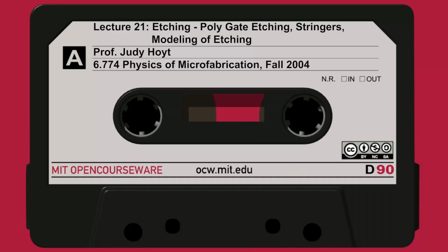On slide 2, this is a chart, or it's half of the chart that I took directly from chapter 10 in your text. And what it shows is a series of common materials and some typical etchants that are used, and then some comments about each of these etchants. For example, a very common way of etching polysilicon in a generic way is to use SF6 or CF4. What are the characteristics of that type of etch? Well, it tends to be isotropic or near isotropic, and not very good selectivity over SiO2. So once you hit the SiO2, you continue etching. So this is a general purpose etch you might use if you're trying to strip off some poly off the back of the wafer or something. Probably not something you might use if you need anisotropy or something like that.